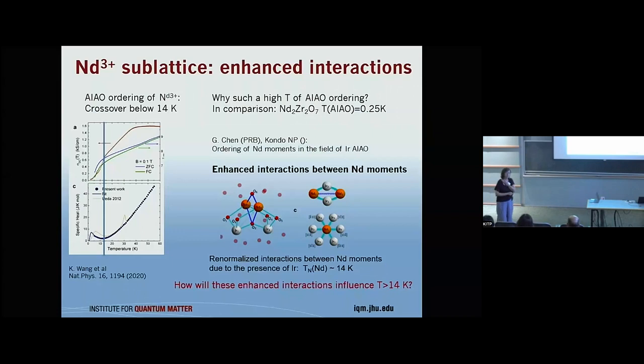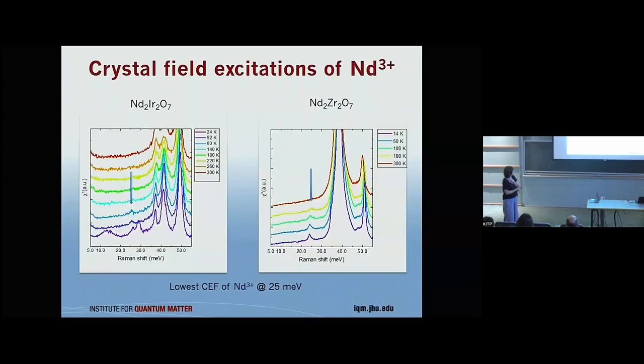Muons cannot measure diffraction. I don't think they go so high in temperatures in diffraction, but muons are very reliable, though there are 2 papers which are plus minus a few K. I'll briefly comment. At 14 Kelvin, there is also this magnon peak from the neodymium that appears in the Raman spectrum. That's where it starts to be visible in the Raman data. Okay, we need to go on.